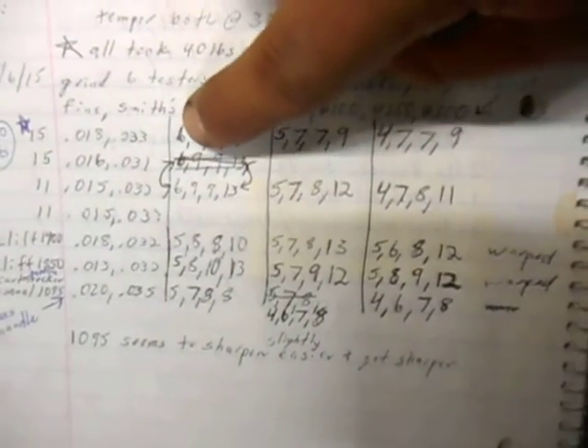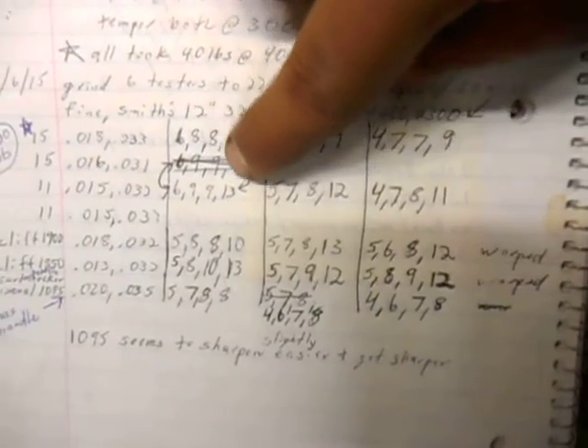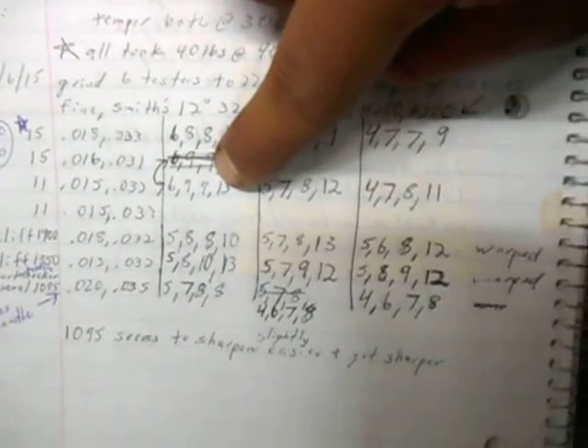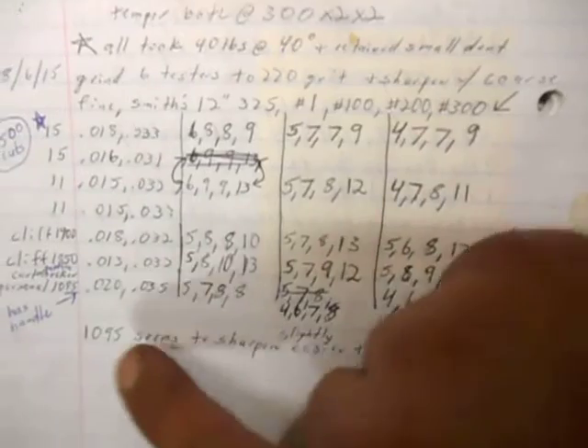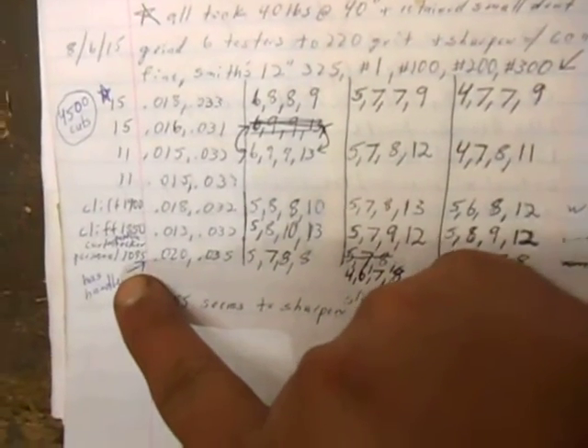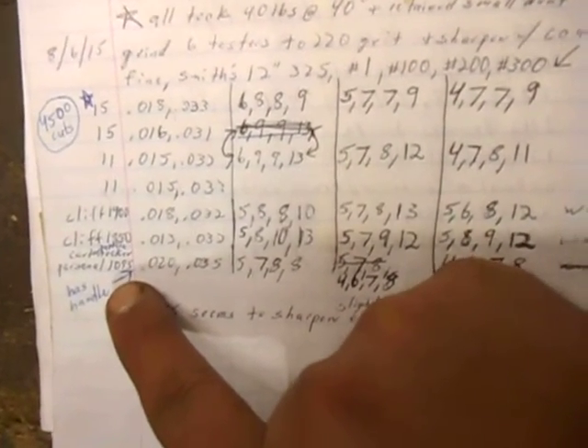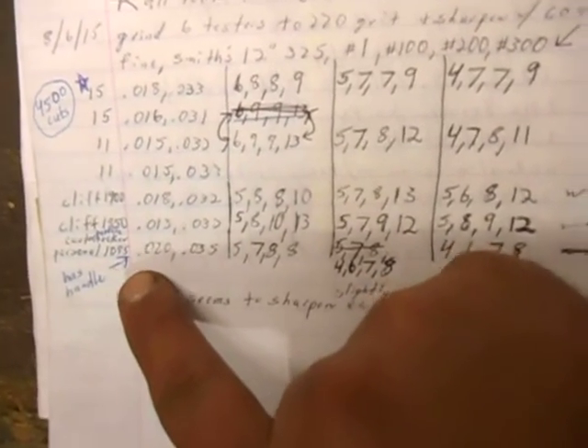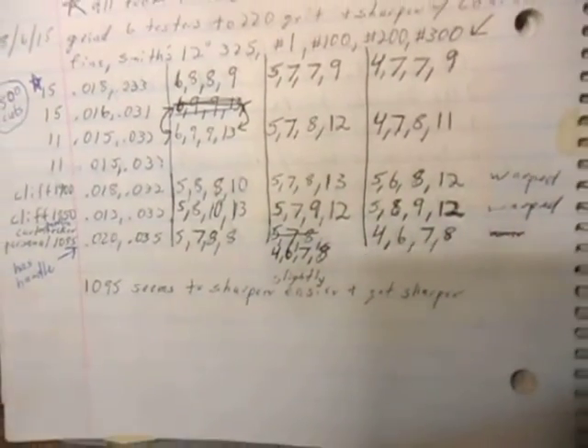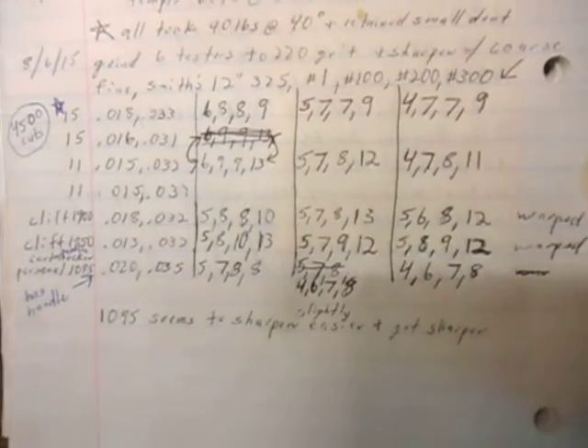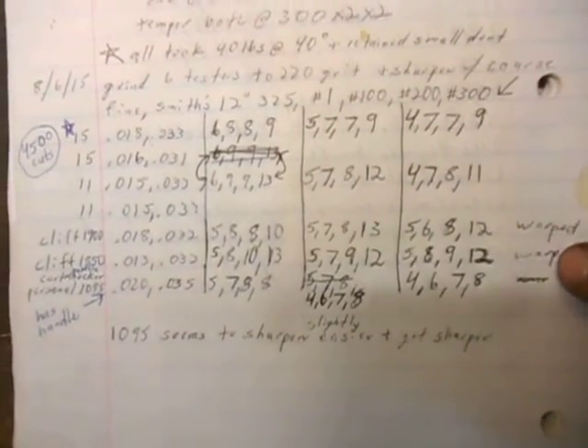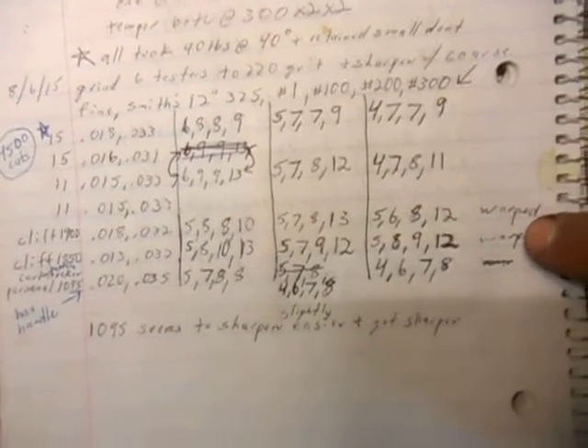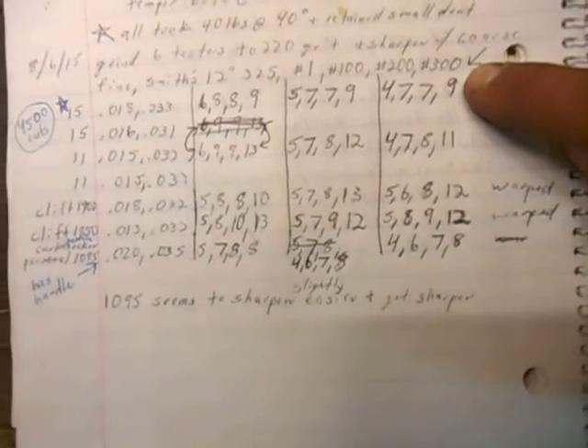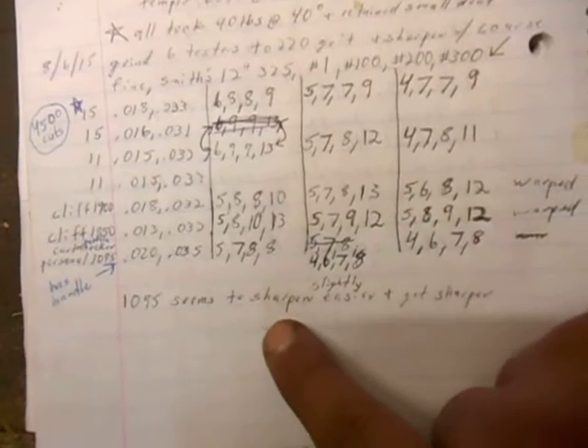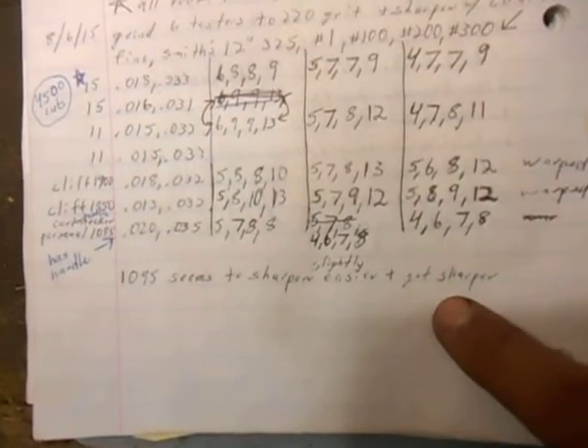This part right here, I wrote that down in the wrong spot, so it's supposed to be there. And then this one also. I also tested my personal Carter pattern necker out of 1095. Now, it also says here that both of the ones that were multiple quench warped slightly, whereas the other ones did not. My 1095 seems a little bit easier to sharpen and seemed to get slightly sharper.